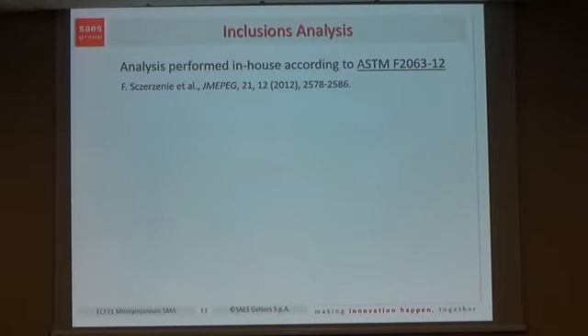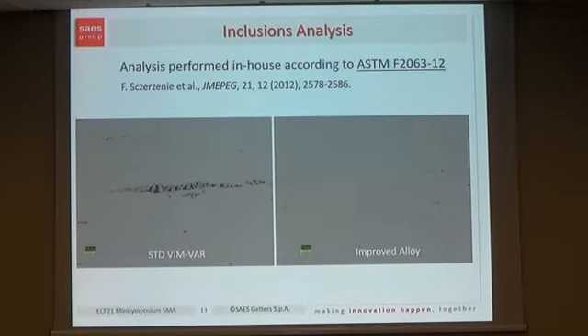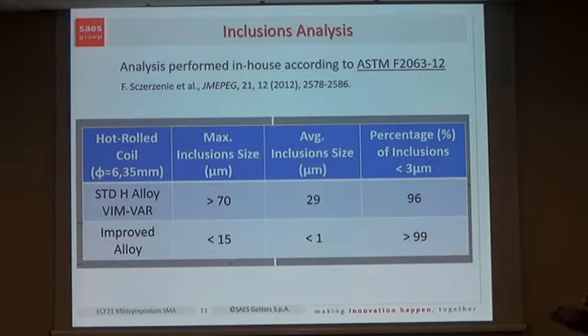Historically we developed an internal procedure, and just to show you a couple of pictures, this is the representation of a longitudinal cross section of a 6.35 millimeter coil. It is a semi-finished product in the range of the standard practice, and the same size of the improved alloys. This is only a qualitative picture, but these are the numbers. The numbers show that on the shape memory formulation, titanium rich, the max inclusion size is reduced by more than 5 times, and the average inclusion size, which is important, of the improved alloys is systematically below 1 micron, with more than 99% of inclusions below 3 microns.